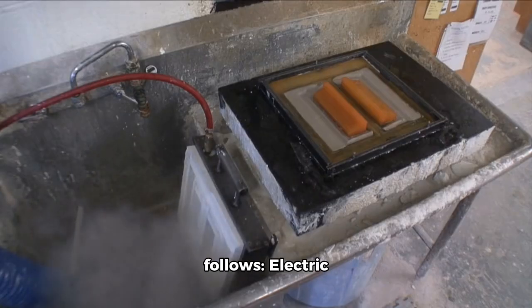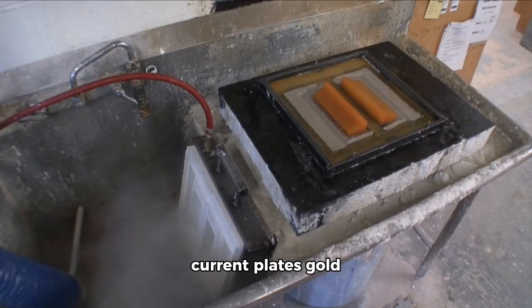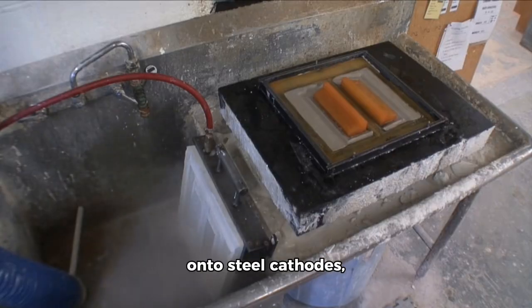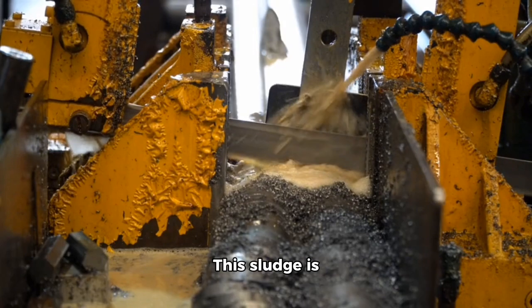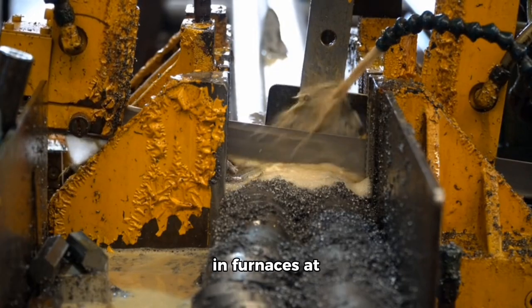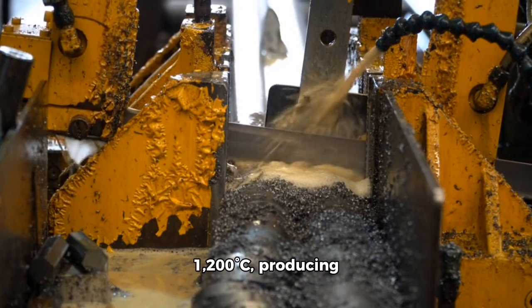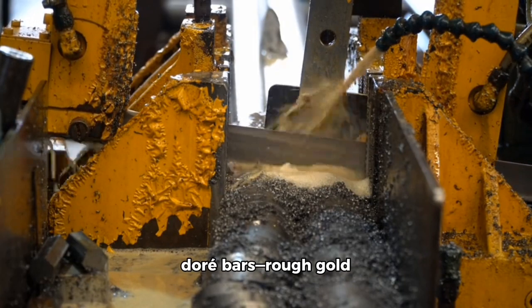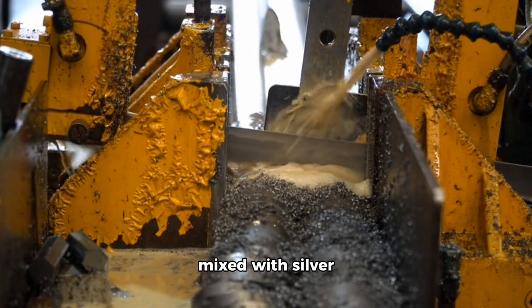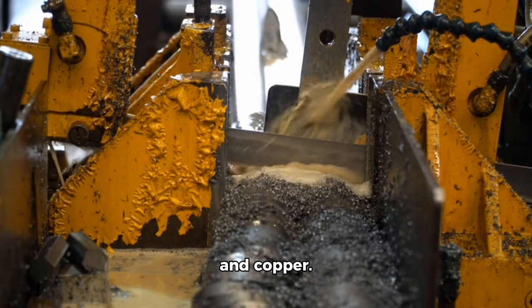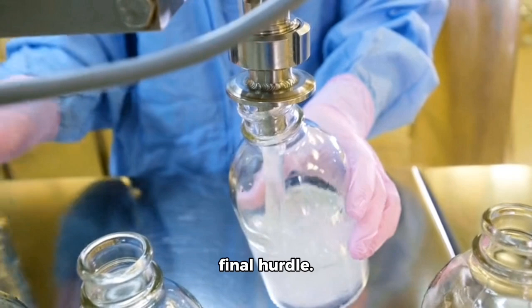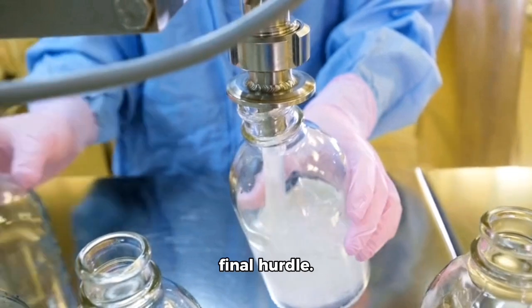Electrowinning follows. Electric current plates gold onto steel cathodes, forming a sludge that's 70 to 80% pure. This sludge is dried, then smelted in furnaces at 1,200 degrees Celsius, producing doré bars, rough gold that's 90% pure but mixed with silver and copper. For 99.99% purity, refining is the final hurdle.